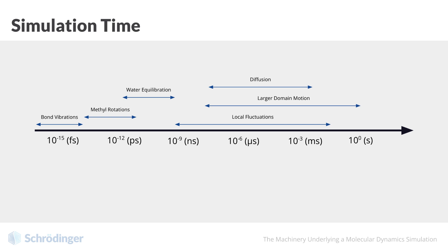Fortunately, with modern advanced GPUs, we can capture the femtosecond to microsecond timescales with MD simulation. For all atom molecular dynamics simulation, our time step will usually be two femtoseconds—that is, the amount of time allocated for one loop in our MD cycle. Our total simulation time will be anywhere from several hundred picoseconds to several hundred nanoseconds, meaning several million loops through our cycle.